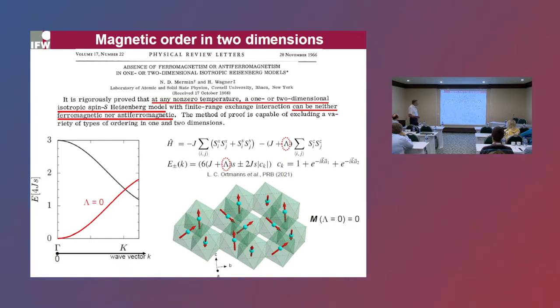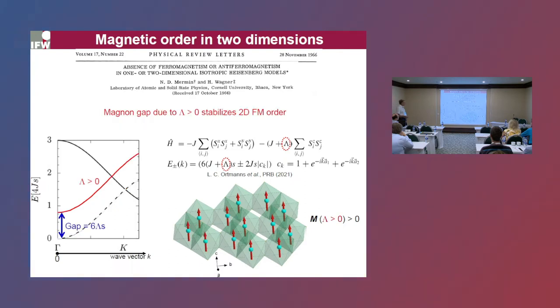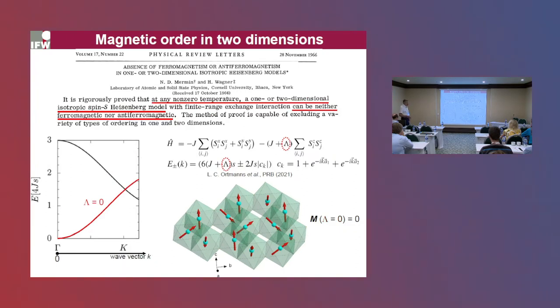The situation may change drastically if one introduces anisotropy, parametrized by lambda. In this case, the energy spectrum acquires a gap which is proportional to lambda. If one switches on positive anisotropy, one can stabilize two-dimensional ferromagnetic order because a gap opens in the excitation spectrum proportional to this anisotropy. If the gap is finite, one has long-range order of the spins in two dimensions. If one closes this gap, the order is destroyed.